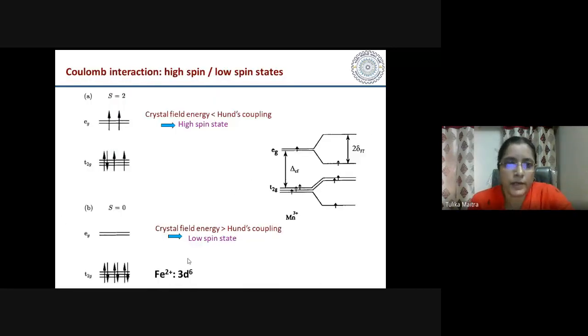Another thing that we can find out is the relative difference between the crystal field energy and the Hund's coupling, giving rise to a high spin state, which is shown here. If the crystal field energy is less than Hund's coupling, then you will have a high spin state, like shown here. Or if the crystal field energy is greater than Hund's coupling, then you will have a low spin state, like shown here. These spin states can be determined by density functional theory calculations. Then one can compare various energy scales in the material under study and write down a model Hamiltonian accordingly.